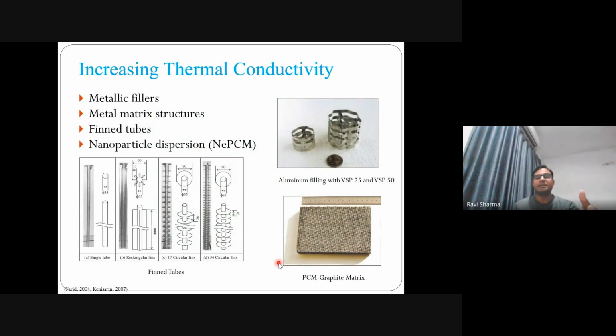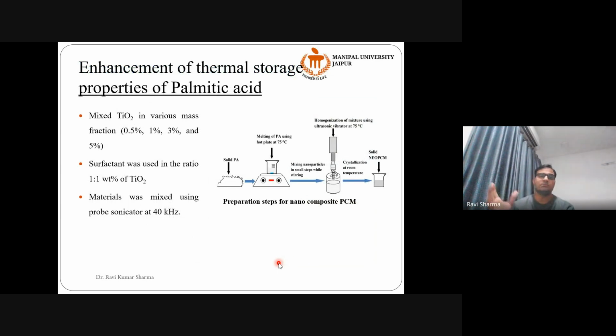So thermal conductivity can be increased by inserting metal matrix, fin tubes, nanoparticle dispersions, etc. There are many ways to do that. We did many experiments for thermal conductivity enhancement. I'll explain one of them quickly. We took palmitic acid as a PCM, solid PA means palmitic acid. This palmitic acid was kept on a hot plate, melted, then nanoparticles were added using a sonication process, and then it was solidified.